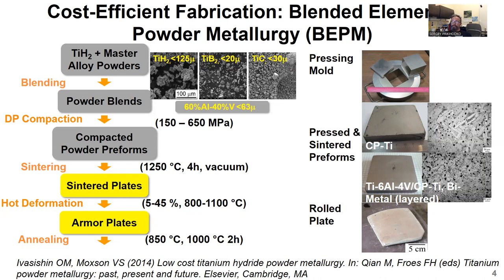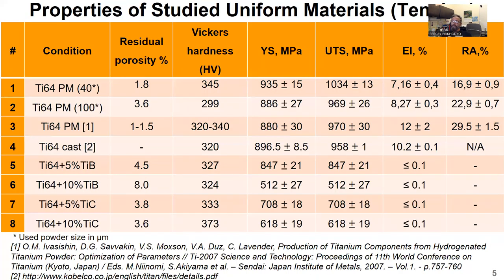We use titanium hydride as the only titanium component in our process. It was shown that the presence of hydrogen in the compact during sintering reduces oxygen and chlorine content, and improves densification of the alloy. This table summarizes mechanical properties of uniform materials made earlier in this study. Mechanical properties are strongly dependent on the combined effect of residual porosity and the fraction of reinforcement. When the amount of reinforcement increases, we observe the expected drop in elongation. However, the anticipated increase in strength is not taking place due to related porosity increase.